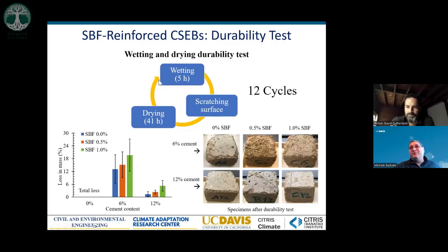To describe the test, fundamentally, what we are doing is we wet the material by submerging it in water for 5 hours. Then we use a metal brush to see how much material gets removed after each of these cycles. Then we dry the material. Once it's dry, we go through that process 12 times. And then we measure the total loss of mass from the different materials. With 0% cement, all of the material was always lost after the 12 cycles. With 6%, the loss in mass was quite significant, about 15% on average. With 12% cement, the loss in mass was well within the limits that are considered acceptable.